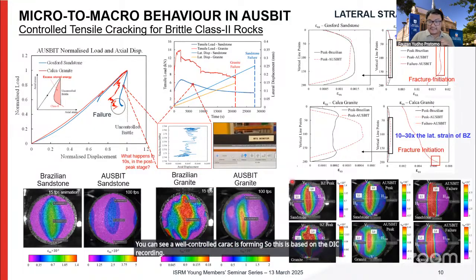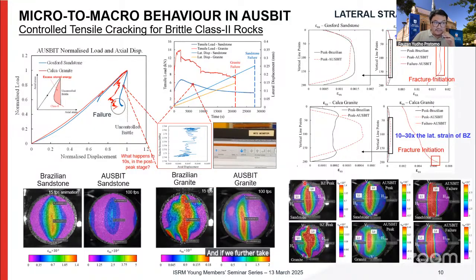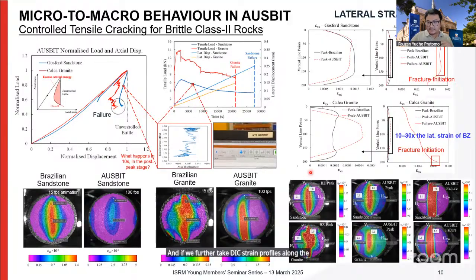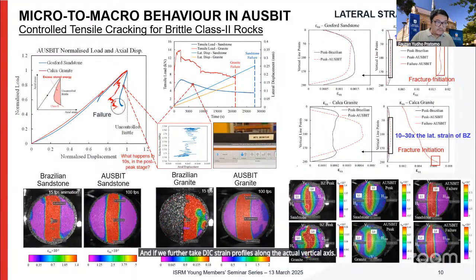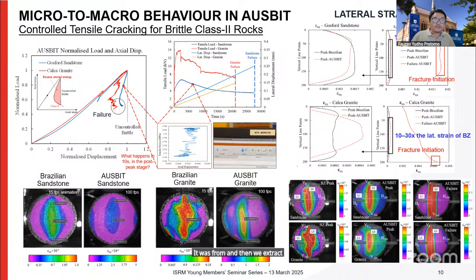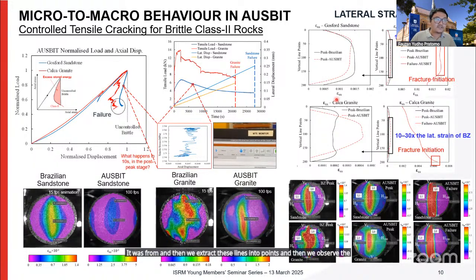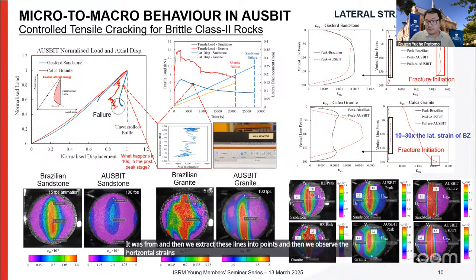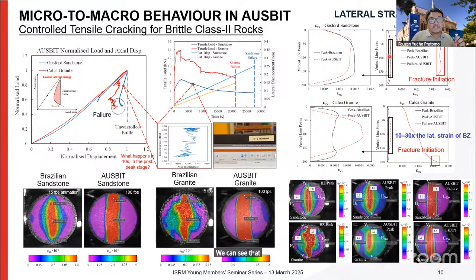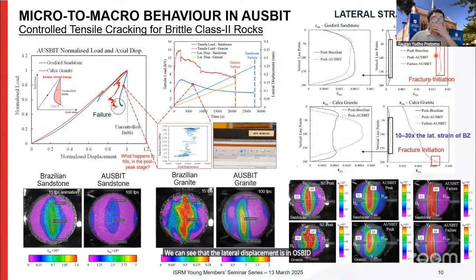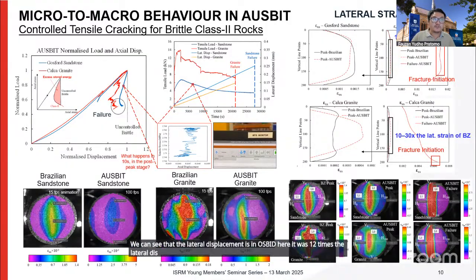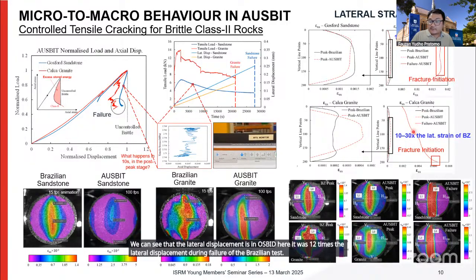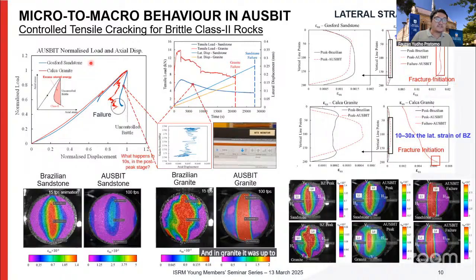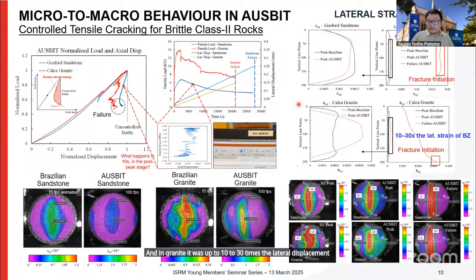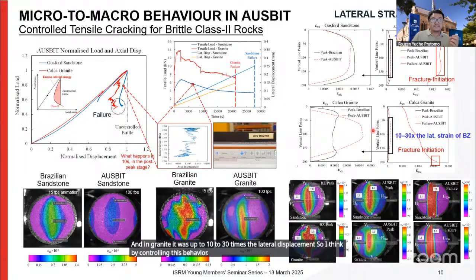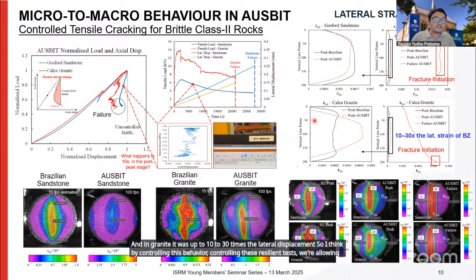And if we further take DIC strain profiles along the axial vertical axis, we extract these lines into points, and then we observe the horizontal strains along each point. We can see that the lateral displacement in AUSBIT here was 12 times the lateral displacement during failure of the Brazilian test. And in granite, it was up to 10 to 30 times the lateral displacement. So it means by controlling these Brazilian tests, we're allowing significant lateral extension before the failing.